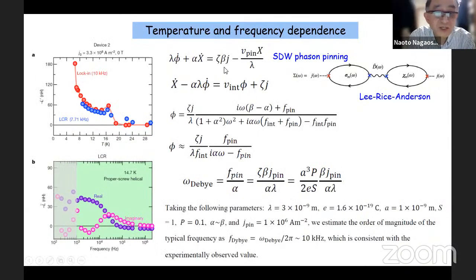But now we are struggling with frequency and temperature dependence of this inductance. So this equation of motion I just presented is in the linearized approximation. And this V pin is nothing but a pinning of the phason. So all this electromagnetic response is actually quite similar to the spin density wave phason pinning problem. So then this diagram first proposed by Lee-Rice-Anderson long time ago applies here also. But this collective mode between these electron bubbles contains uniform magnetization and the phason degrees of freedom. So both components will contribute to the electromagnetic response of these systems. But in any case, this Debye type relaxation formula is derived.